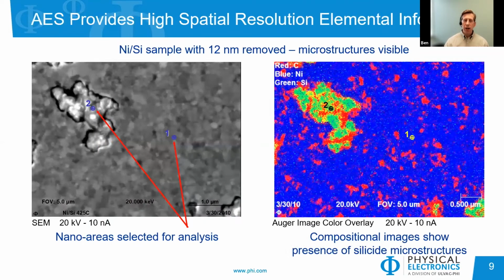And the power of Auger is in the high spatial resolution. Since we're using an electron beam, we can get down to single nanometer type of beam sizes. So that gives us very good spatial resolution on our samples. As you can see here on this material, this is a nickel silicon sample with a lot of texture that we can see in an SEM image.